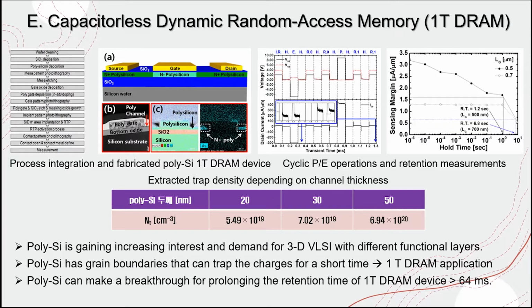compared with the one-transistor one-capacitor conventional DRAM. The six-sigma tail is located at 64 milliseconds for the conventional DRAM, but in one-transistor DRAM the retention is mostly determined by the diffusion of very fast diffusing carriers programmed into the floating channel. So there should be some ways. I should have prepared some different methods other than storing the carriers within the electrical barriers. One thing is to introduce polysilicon. Polysilicon is used everywhere, right?